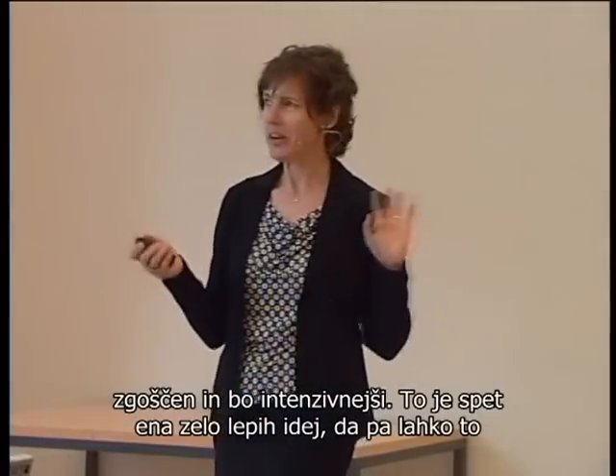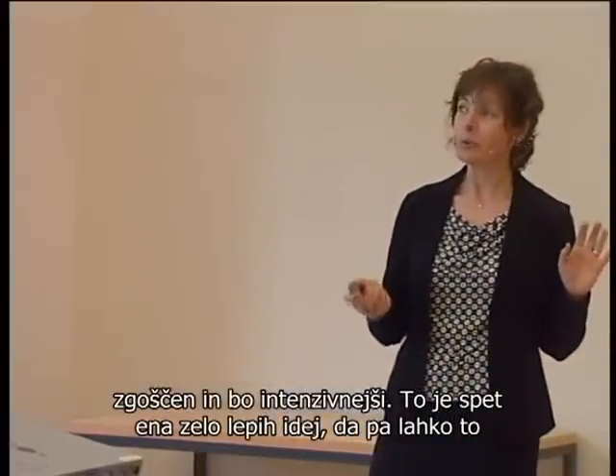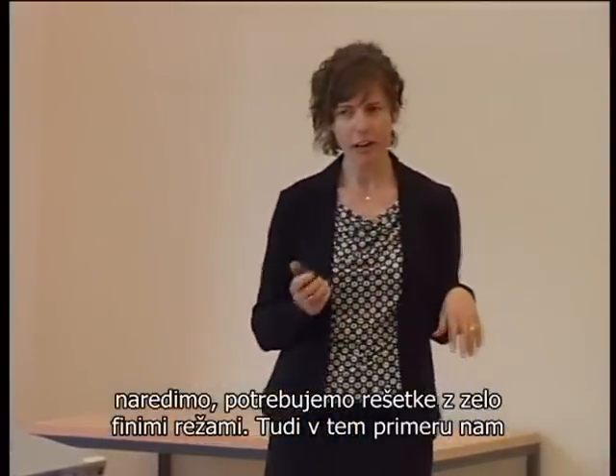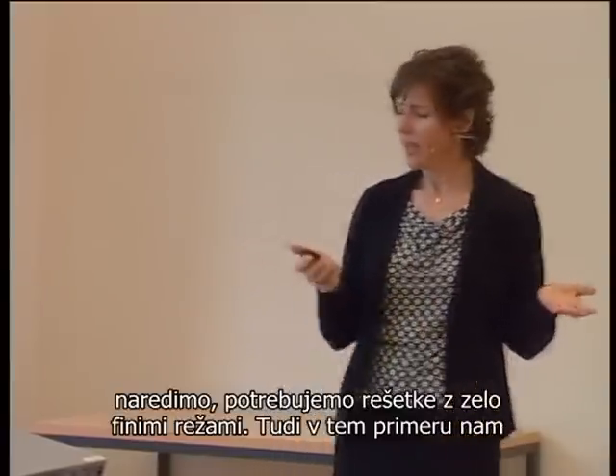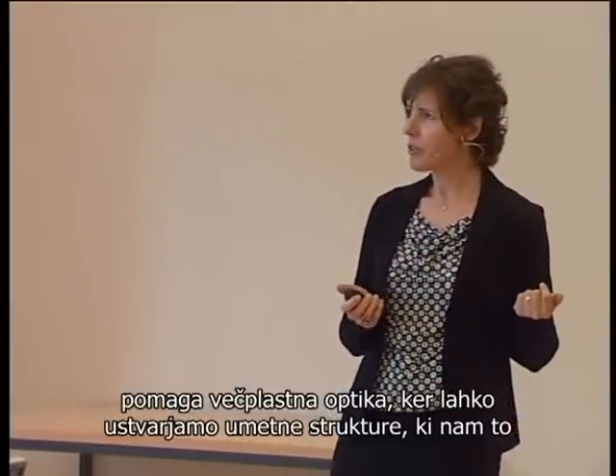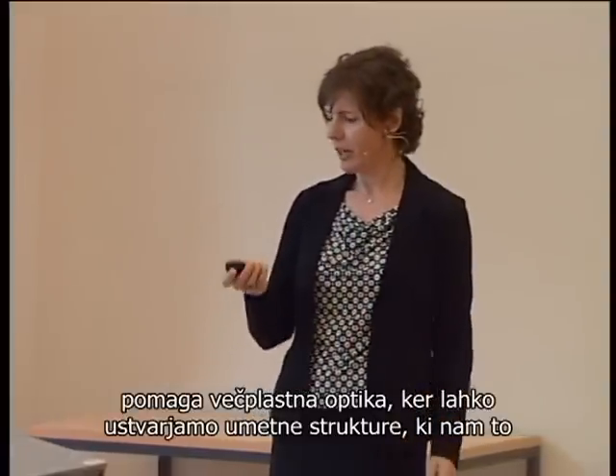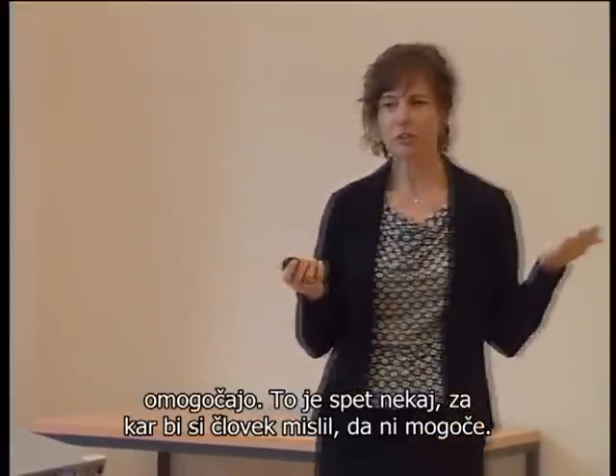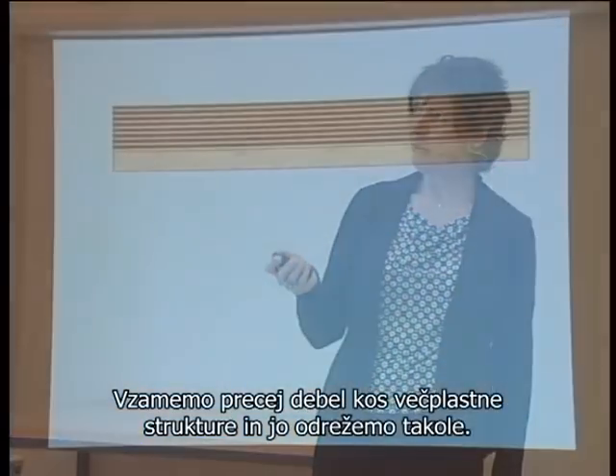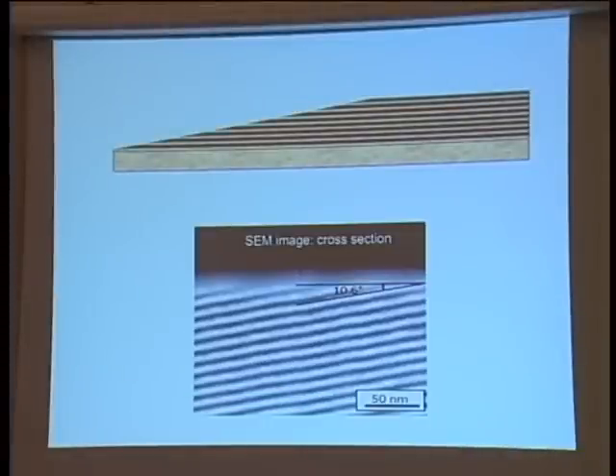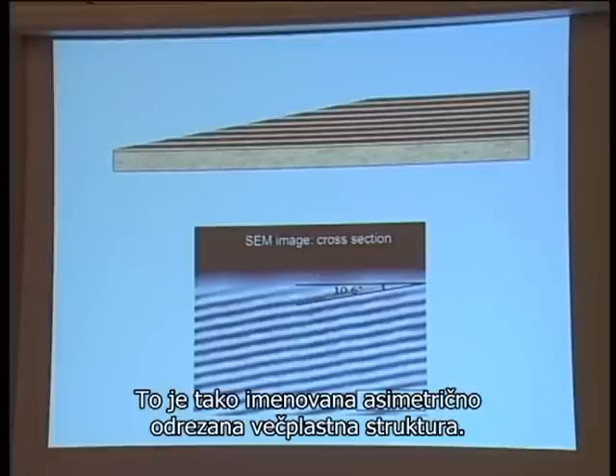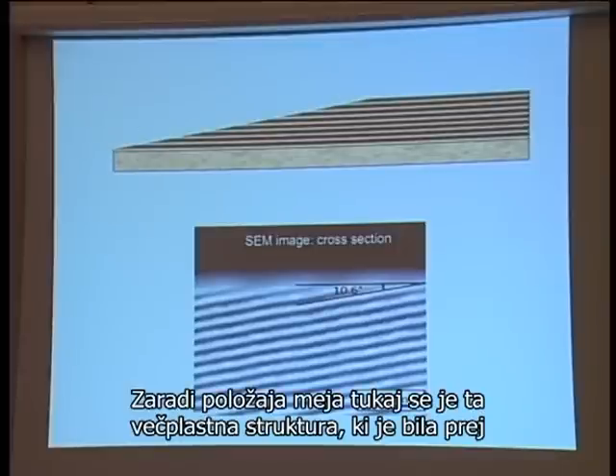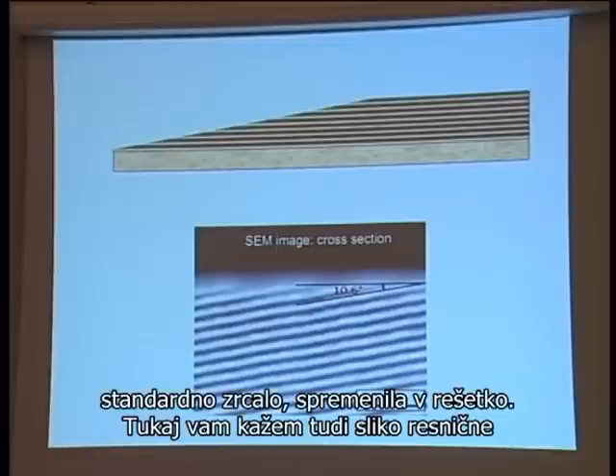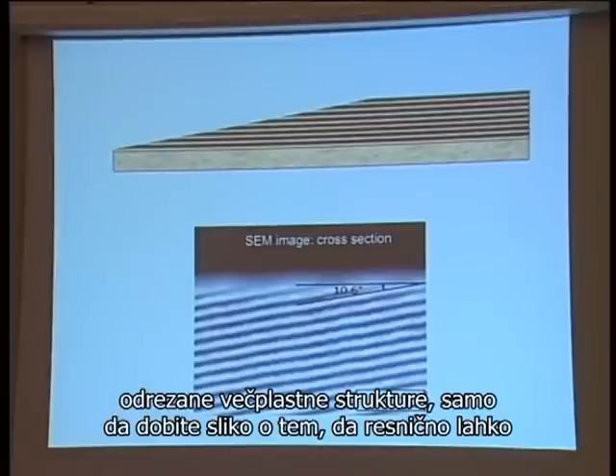Again, this is a very nice idea. However, to do this with X-rays, you need gratings with a very fine grating pitch. Again, in this case, multilayers come to help us because we can create artificial structures that enable us to do something that you would not think is possible. We take a rather thick multilayer and we cut it like that. This is a so-called asymmetrically cut multilayer. Due to the boundary condition here, this multilayer that was before just a standard reflecting mirror now acts as a grating.